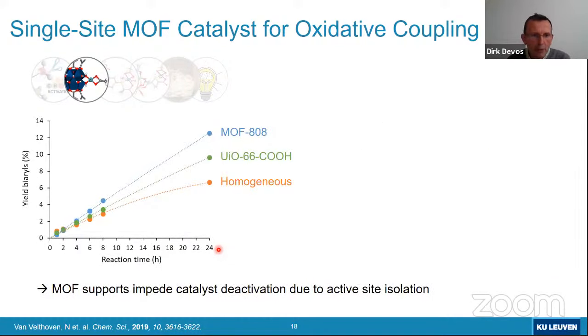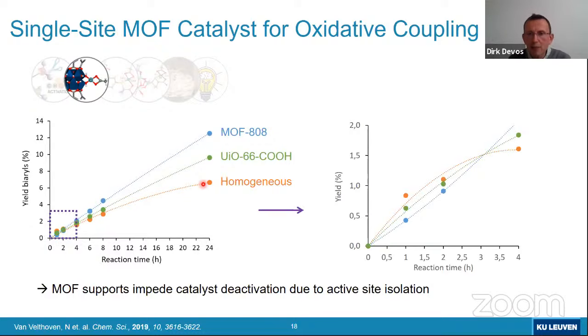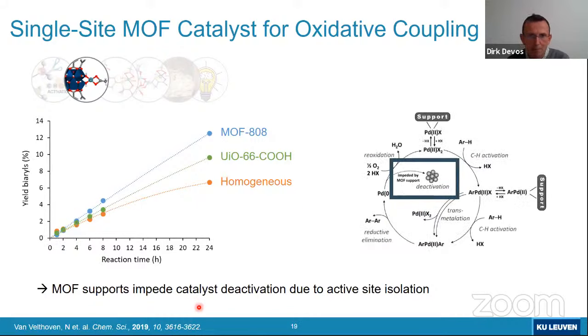And so how does this actually work? This becomes clear if you look in more detail at the kinetics. So here we plot the yield of the bi-aryls as a function of reaction time. And then you see how remarkably linear the reaction course is for the palladium on MOF-808, and to some extent also for the palladium on the UiO. And on the homogeneous catalyst, you can see indeed that there is a deactivation. And that becomes even more clear if you zoom in on the first few hours of the reaction, then you see that immediately you have this deviation from linearity for the homogeneous catalyst, whereas with the MOF catalyst, the blue line here, it's a linear curve. So essentially the MOF support impedes the deactivation of the molecular palladium catalyst.